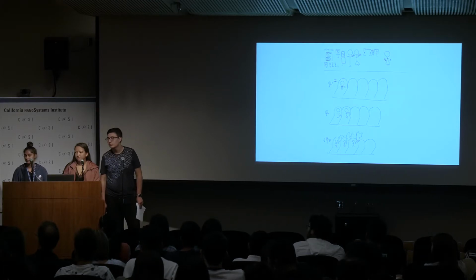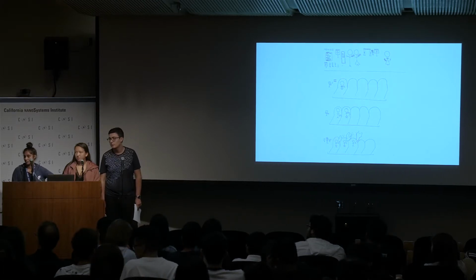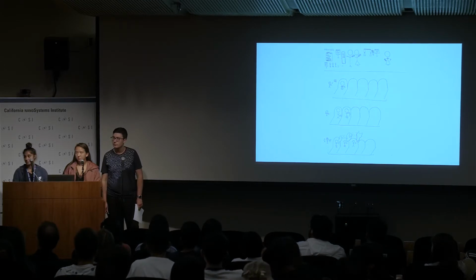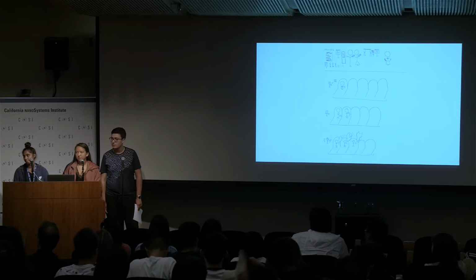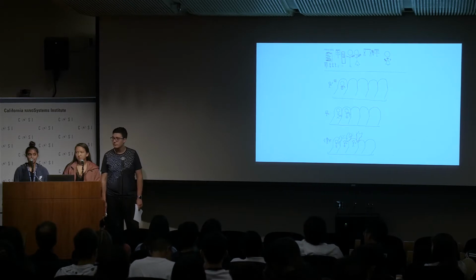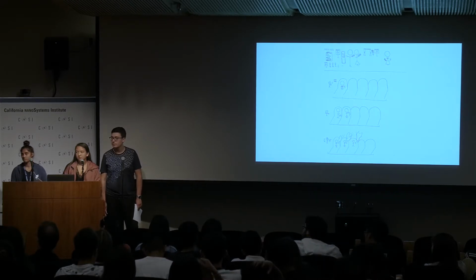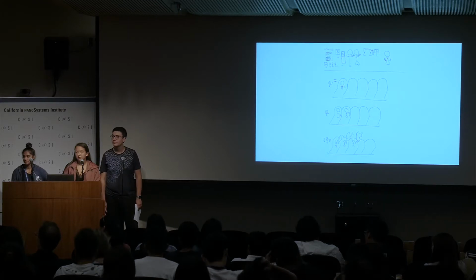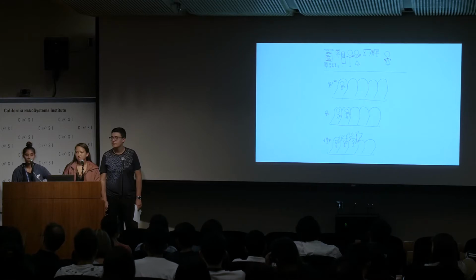The ions, right? So it's always ions that are doing the damage, but in the case of the nanoparticles, it's able to release the most ions into the cell because it, as a whole chunk, gets into the cell, whereas the ions have to go in individually and it's slow, and the bulk releases so few of them, right? So good. Just wanted to make sure that was clear, because I know that with the children being actually smaller than adults, that could be confusing.